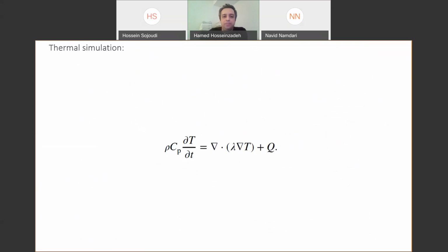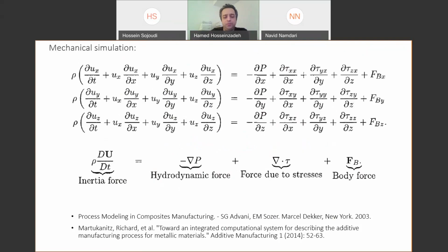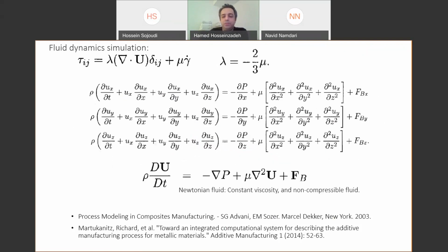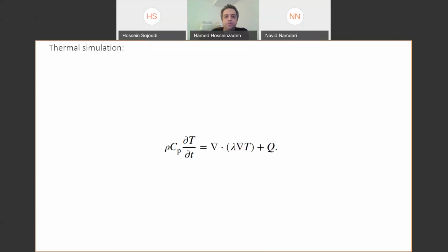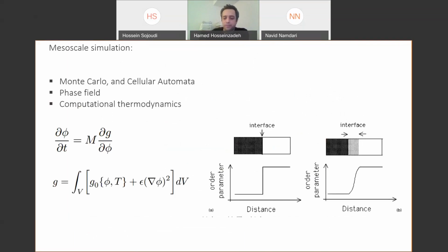So for metal 3D printing, if you want to calculate the thermal stress or residual stress, you need to use this form of momentum equation. If you want to simulate the melt pool, we need to use Navier-Stokes equation, but because we have a free surface, we need to add some other method. For example, volume of fluid or other methods to capture movement of the surface of the melt pool, but this Navier-Stokes with some assumptions is working very well for metal additive manufacturing, and also for thermal history, we need this equation. They are very commonplace and simple to use.